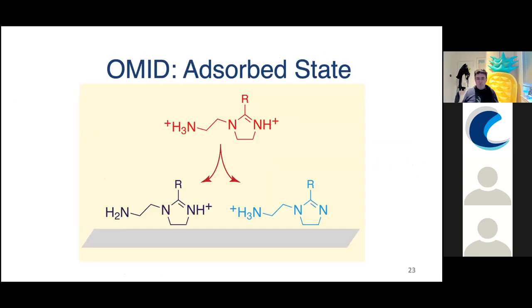So in summary, the adsorbed state looks like this, going from doubly protonated in bulk solution to two singly protonated states on the surface, with the one on the left-hand side being the primary species. However, I haven't told you anything about what the surface looks like at this point. What does this interface look like? Because that's also important. What are the molecules adsorbing onto?